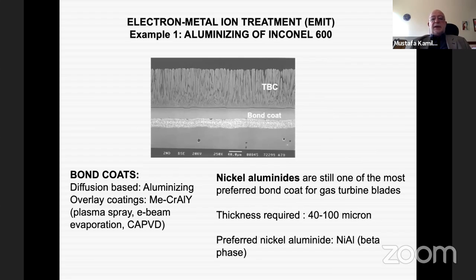And the first study that we have conducted for this purpose is aluminizing of Inconel. Inconel is a nickel alloy, as we all know. These materials are used for high temperature applications, and the surface of these materials must be protected from high temperatures by a thermal barrier coating. For a good adherence of thermal barrier coating to the substrates, we need a bond coat. These bond coats are metallic in nature. They can be metal, chromium, aluminum, yttrium-based structures that can be produced by plasma spraying or E-beam evaporation,